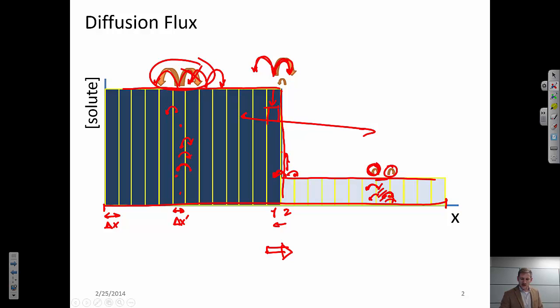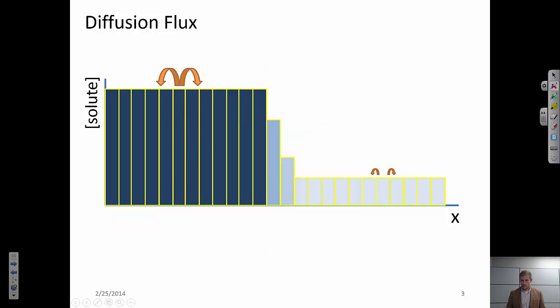So what this means is that within a given time step I'm going to decrease the concentration here and increase the concentration here. Now remember, on an atomic scale all those atoms are moving around randomly. They're equally likely to move to the right or to the left. But what is changing our compositional gradient here is the fact that if I do have a gradient, I'm more likely to move downhill than I am to move uphill.